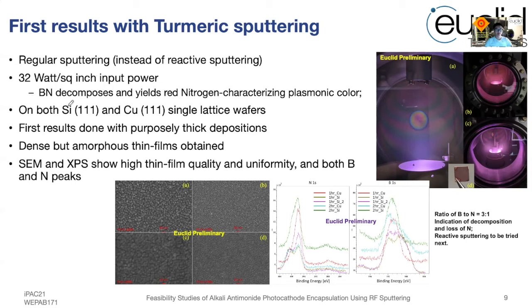We did the sputtering on both silicon 111 and copper 111 single lattice wafers and characterized those thin films later. We found that the thin film on the wafers was very dense, but also amorphous. We did a long sputtering session for each sputtering because we wanted to see the thin film clearly. And although this is not necessarily a single lattice structure, the thin film quality was shown under the SEM and XPS to be very high. With this thin film, we are sure that, without considering the QE effect yet, this will protect the substrate from oxidation or humidity in air.